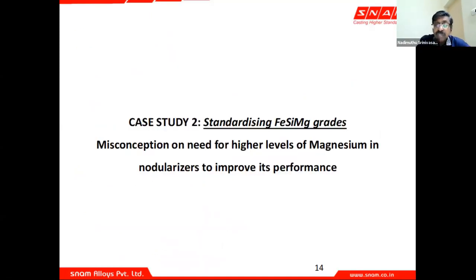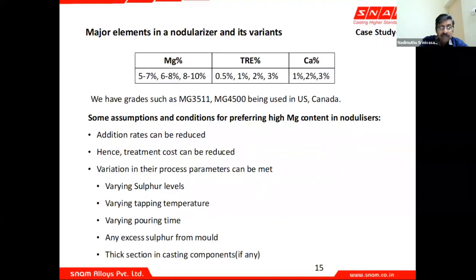Now the next is on standardization of ferrosilicon magnesium grades. So if you look at the experiment that I had just shown you, I had shown you 3 different grades of ferrosilicon magnesium. A lanthanum-based ferrosilicon magnesium, and 2 with varying percentages of magnesium. One was 7% nominal and the other was 9%. Now, these are the grades that we find mostly in India with 5 to 7%, 6 to 8%, and 8 to 10%. We get inquiries where people want even more than 10% magnesium. And in terms of the rare earth, from 0.5, 1%, 2%, 3%. Calcium 1, 2, 3. Now, every addition is going to cost money, right?